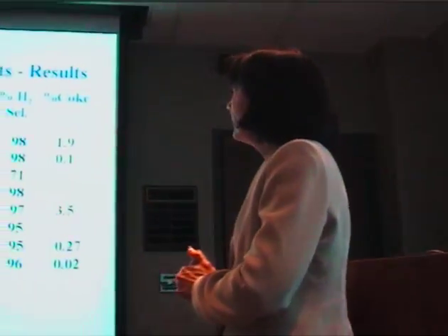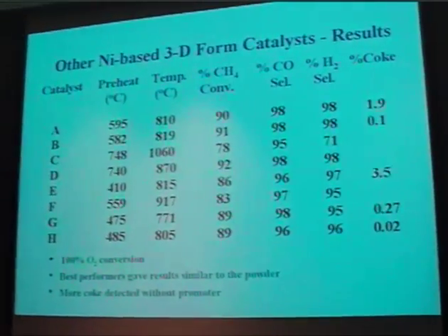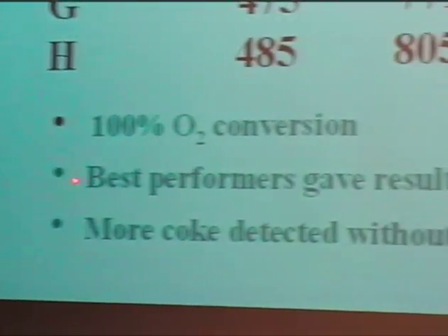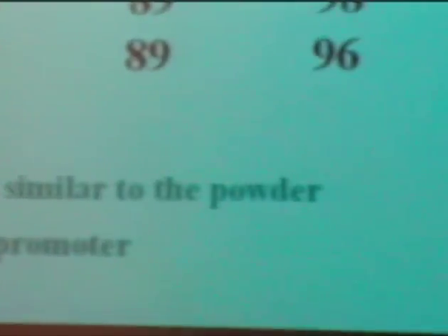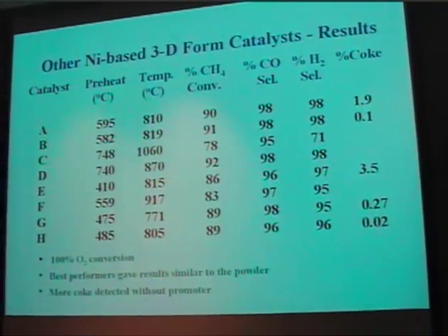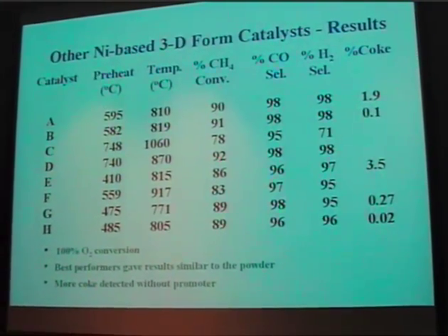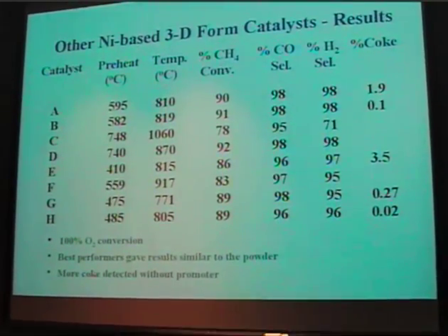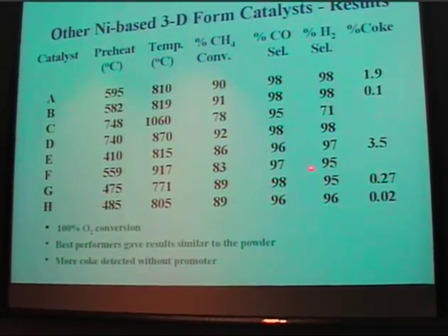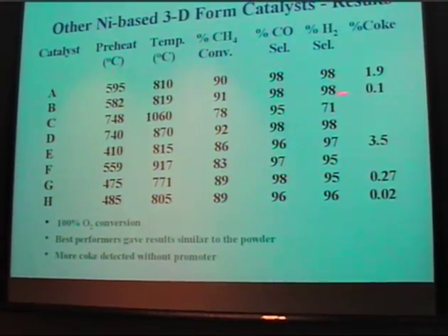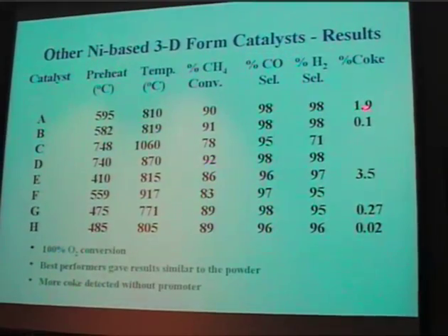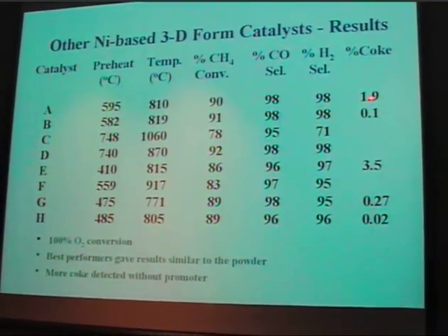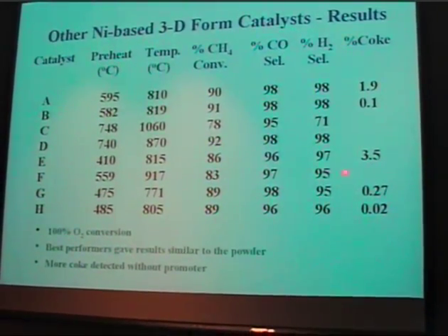So again, the data that's out there in the patents are shown here. You may not remember what A through H are, but basically the data is saying that you can support these nickel catalysts on a three-dimensional form. It looks very attractive because we're getting reasonable conversion and selectivities. A is the one that was nickel without the promoter, so we did see quite a bit of coke forming there. And I forgot what E was. I can go back to that one.